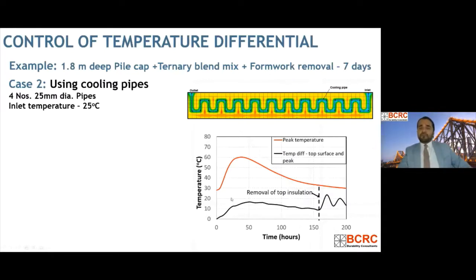So what happens then? Now we can see that we have significantly reduced the peak temperature, right? From 70 degrees in the previous example, we have reduced it to 60 degrees, right? Not only that, we have also reduced the temperature differential, right? So this is the formwork insulation removal time, which is 7 days that we considered in the previous example. But this time we're only looking at a temperature differential of 24 degrees, right? And a peak temperature of 60 degrees.